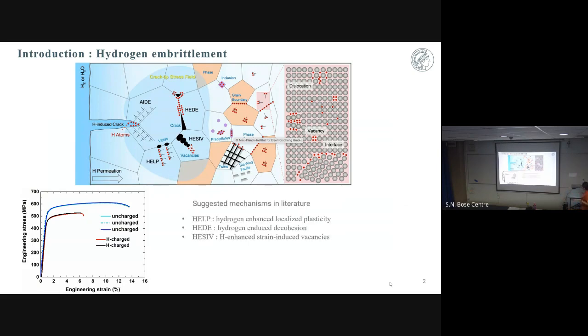The most popular mechanisms in literature are the following: hydrogen enhanced localized plasticity, which mostly means that in the presence of hydrogen the local environment is modified and local plasticity mechanisms are introduced. Here it talks about how hydrogen promotes decohesion, and this talks about the presence of hydrogen promoting strain-induced vacancies.